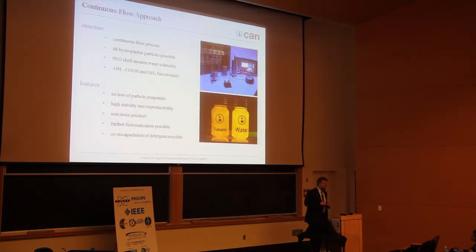So how do we do this encapsulation procedure? I think you already guessed it, it's a continuous flow procedure too, because I think there's not much sense in trying to get the best reproducibility in the synthesis and then to end up with a bad reproducibility during the phase transfer. So we do a continuous flow approach here too. What we need is in principle only a microfluidic mixing chamber, like I have here. And here we add the water and the particles with the polymer so that the micelles are formed within this mixing chamber. And let's check the reproducibility of this.